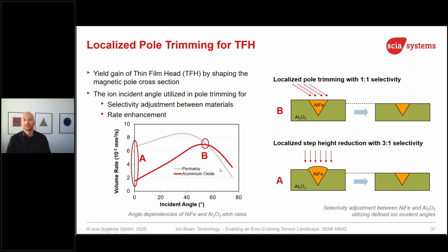Problem now: in ion beam etching, the sputter yield is different for all the different materials. If you look at that diagram here, how our etching rate is changing versus angle of incidence, we see that at 0 degrees, so perpendicular angle of incidence, this magnetic material is etching 3 times faster than this alumina. It's actually not working. We don't want to create any step. But luckily, we are able to adjust for that with the ion beam trimming tool. We can change the angle of incidence during our process. And there is a working point which has the selectivity of 1. And actually, this one is used in production. So we use it at 55 degrees. We can do this etching process and adjust this write head thickness without creating any step here.